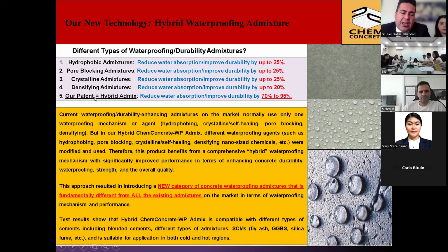Before introduction of our admixture to the market, concrete waterproofing admixtures were mainly classified into 3 to 4 groups: hydrophobic or water repellent admixtures, which can reduce water absorption or improve durability by up to 25% in the best case; pore blocking admixtures, which, same quality, can reduce water absorption and improve durability by up to 25%; crystalline admixtures, which are somehow known as self-healing admixtures as well. They can reduce water absorption or improve durability by up to 25%. And densifying admixtures, which, the same, are less effective, and they can reduce water absorption and improve durability by up to 20%.